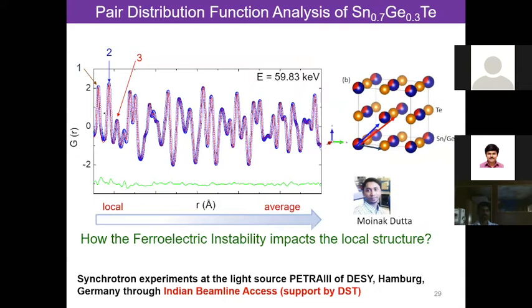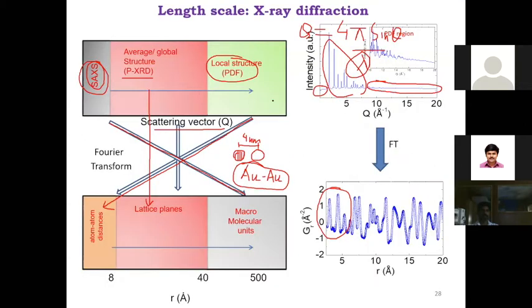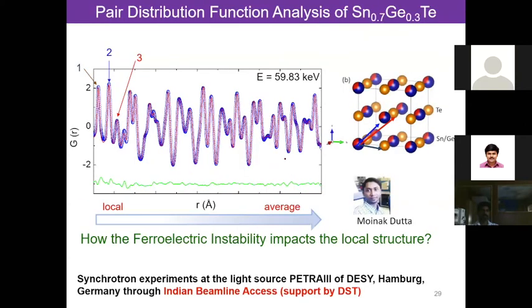So if the fitting is good with a crystallography model for the first two peaks, the local structure is well described. But if the fitting is worse at higher R values, that means the global structure is not well described, and vice versa. So we have to seek a fit for both the local peak as well as the global peak of this X-ray pair distribution function, so that we can explain both local and global structure at the same time. Okay, so now how to do it?